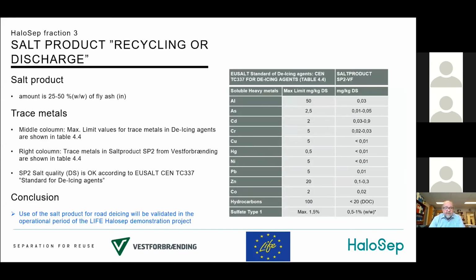The third product, or the salt product, is about 25 to up to 50% of the incoming fly ash. In the table on the right, I've shown the max limit values for trace metals in de-icing agents from TC337. The right column shows the trace metal in the salt product from Vestforbrænding. What you can conclude from these figures is that the salt quality is okay with respect to using this material for de-icing agent. The use of the salt product for road de-icing will be validated in the operational period of the LIFE HaloSep demonstration project.